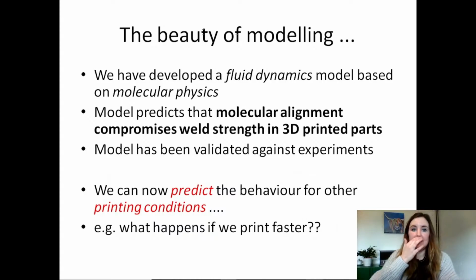So now we're really getting somewhere, right? We've developed a fluid dynamics model. It's based on the molecular physics of this molten plastic material we're interested in. And our model predicts that molecular alignment due to the printing flow is going to compromise our weld strength in 3D printed parts. And what's even better is that we've validated this prediction against some experiments as well. What's the beauty of modelling is now we can predict the behaviour for any other print condition we like without having to perform any further experiments.